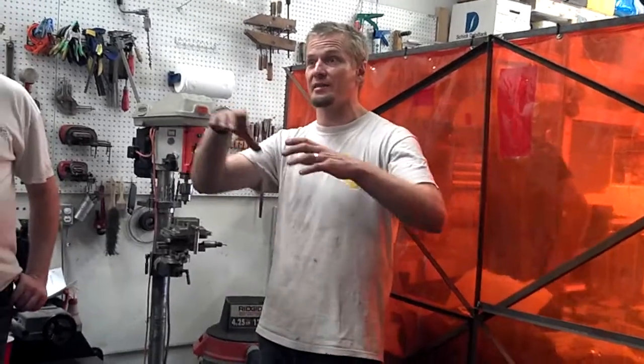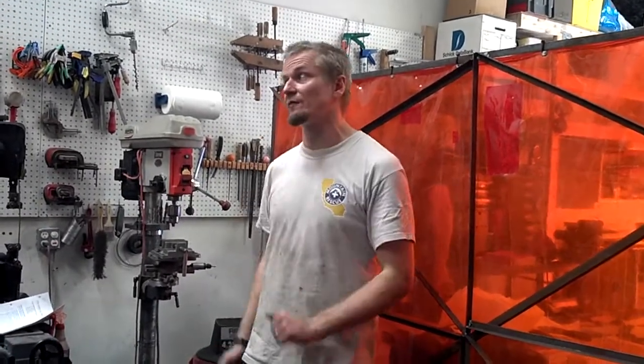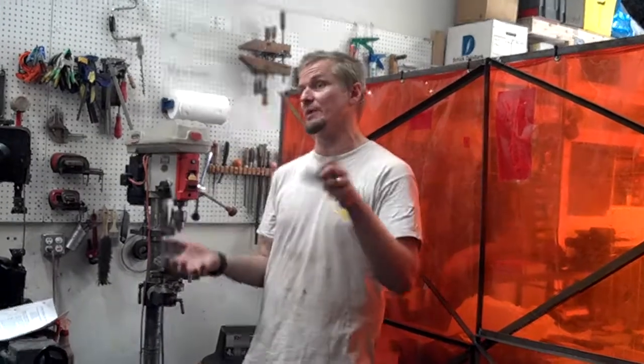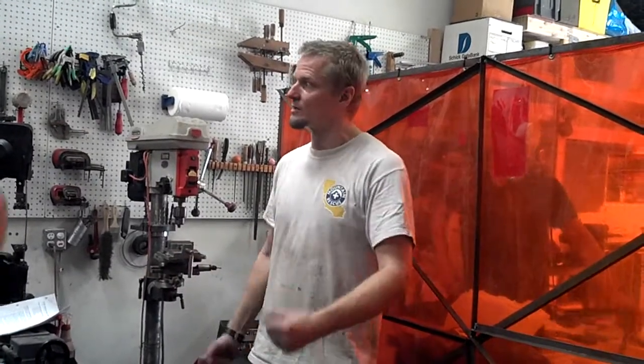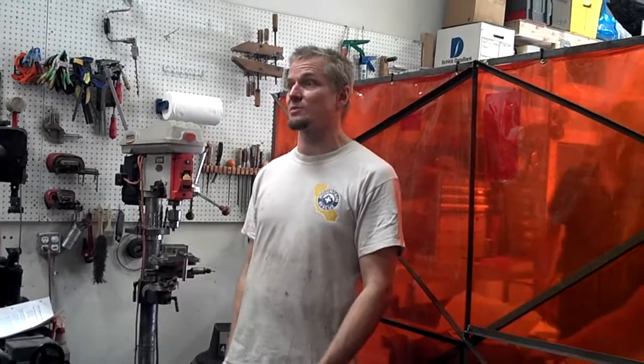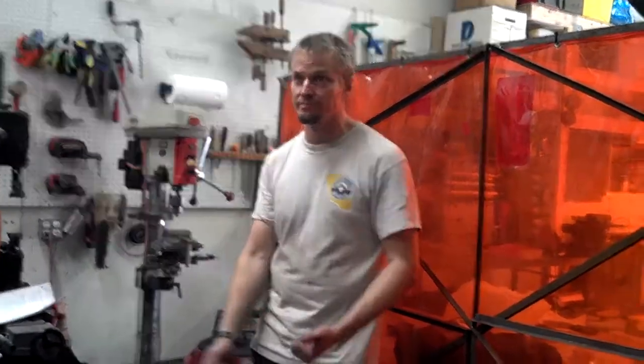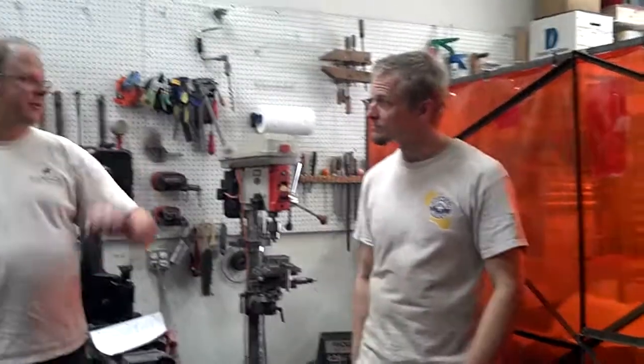We made a quarter-inch thick 4-inch angle iron, pretty heavy steel. But if you go slow and you attack the corners, and let it cool down, and go slow, you get enough penetration. We laid a lot of weld bead to make sure it held, but it worked. You can do stuff if you have the patience to do multiple passes and whatnot. Run over it again. So you guys made it and anchored it into the rocks?